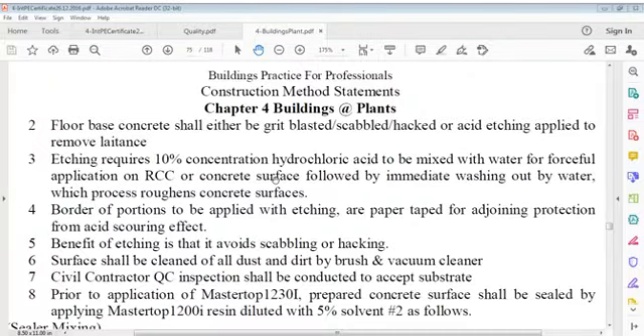Purpose is to remove laitance from surface. It can be done by blasting, that's grit blasting. It can be done by scabbling. It can be done by hacking, or by the method of acid etching. Now etching requires 10% concentration hydrochloric acid, HCl, to be mixed with water for forceful application on RCC or concrete surface, followed by immediate washing out by water, which process roughens concrete surfaces.